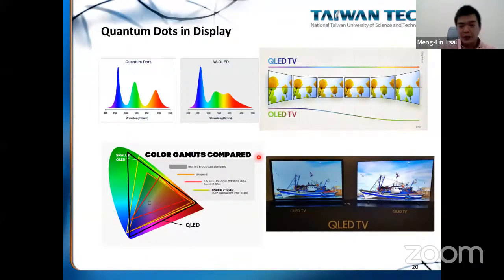And if we compare with OLED TV, OLED TV usually comes with a white pixel to improve the brightness of the OLED. But the white pixel is actually designed by using a blue OLED with a yellow phosphor. So there will be some additional emission around the yellow range, so actually your area will not be very large. But by using quantum dot, you can see three different narrow emission peaks coming out, so this can largely improve the color performance of the display.